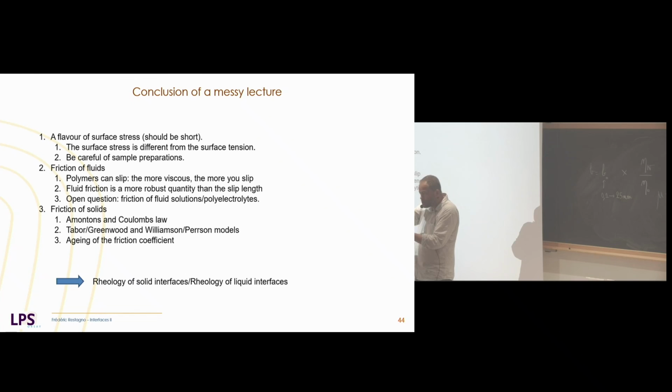And the point is that measuring a friction coefficient after I stop, and the fact that it is difficult to measure a dynamic friction coefficient which decreases with velocity, is that it is an unstable system. Because I push, the friction coefficient decreases, so it will be easier for me to push faster, and that is what is at the origin of the stick-slip that we measure in solid friction. So it is really hard to apply a constant velocity profile when we do this kind of experiment.